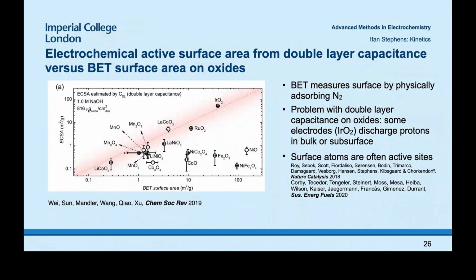And here's a plot comparing electrochemical surface area measured from double-layer capacitance versus BET surface area. You can see there's not always a strong correlation between the two. Part of the reason is that when you're measuring electrochemical surface area, especially on oxides, and this plot is mainly showing oxides, you're not only adsorbing protons at the surface; the oxide has a lot of capacitance in the bulk or the subsurface. You're intercalating protons in and out. So you're not necessarily measuring a surface area, so this axis is actually wrong, even though, for catalysts, usually it's the surface atoms that are the active sites.